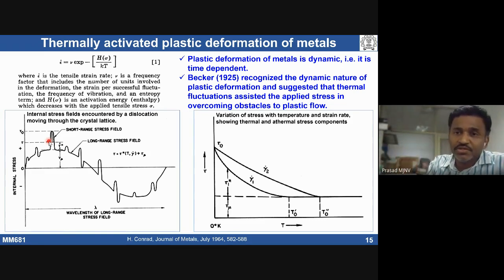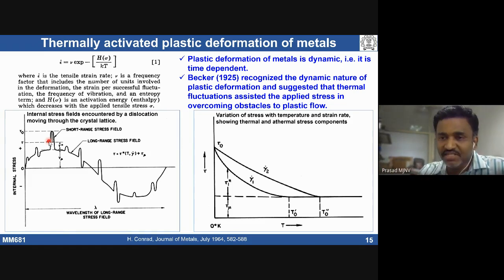So the thermal barriers are already given. One of the best examples is the Peierls-Nabarro stress, which involves the atomic level, 2 to 3 atoms spacing only. And another thing, forest dislocations, because a dislocation is going to thread the gliding planes. Forest dislocations that are present can act as barriers. Lomer-Cottrell locks are also barriers, which are small, within the atomic level.